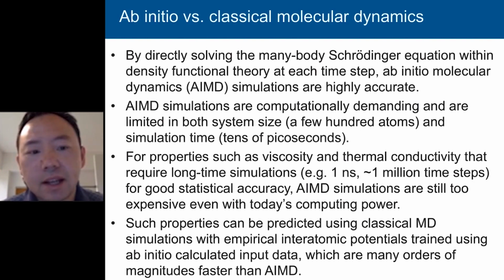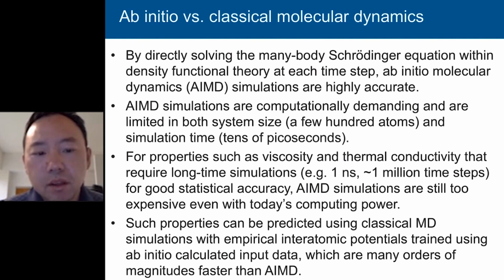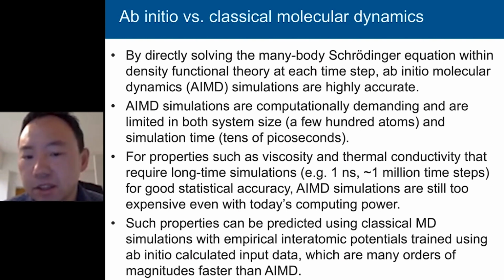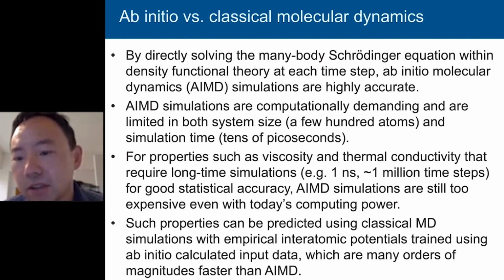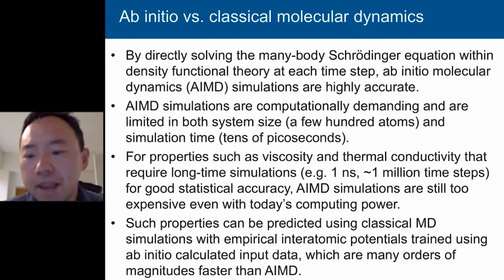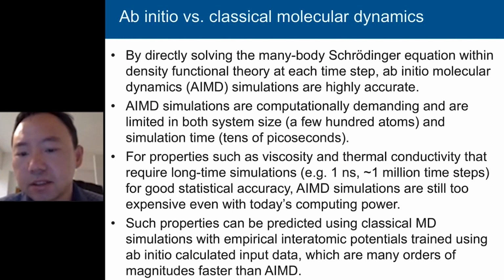They are limited in system size to a few hundred atoms, and the simulation time is limited to tens of picoseconds. So this kind of calculation can easily take weeks or months if it's very large scale. So unfortunately, for some properties such as viscosity and thermal conductivity that are vital to the MSR campaign, they require very long time simulations, such as 1 million time steps, in order to get a good statistical accuracy.